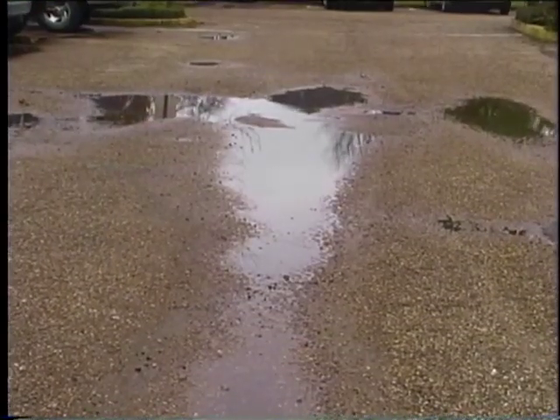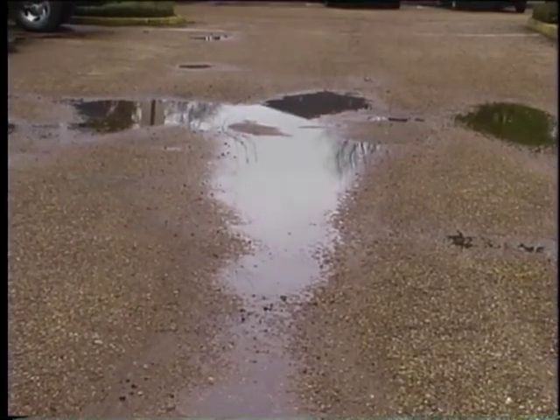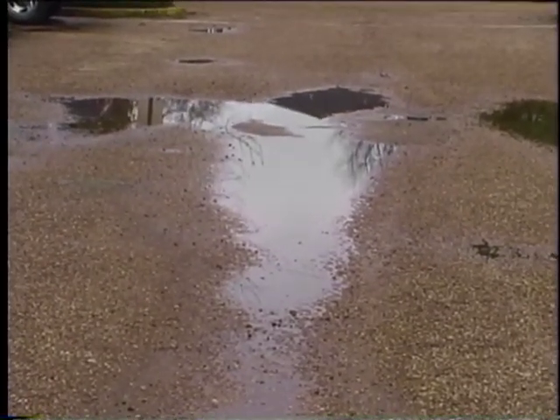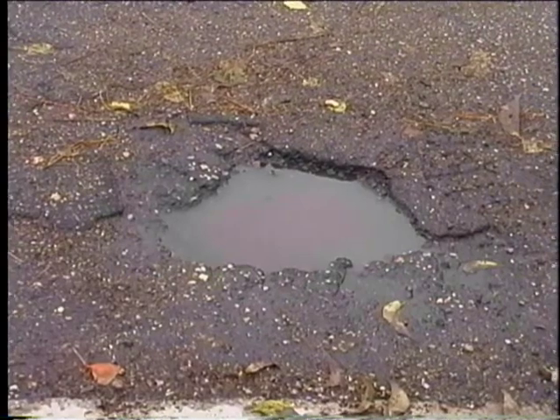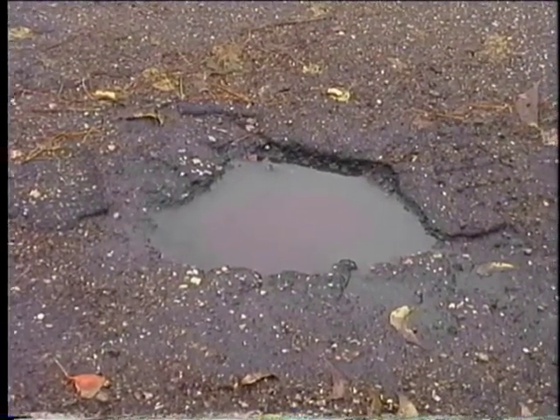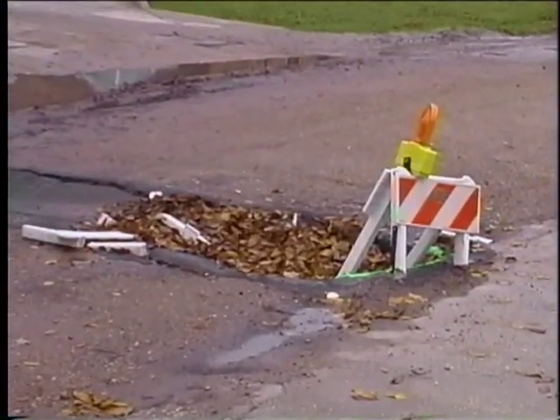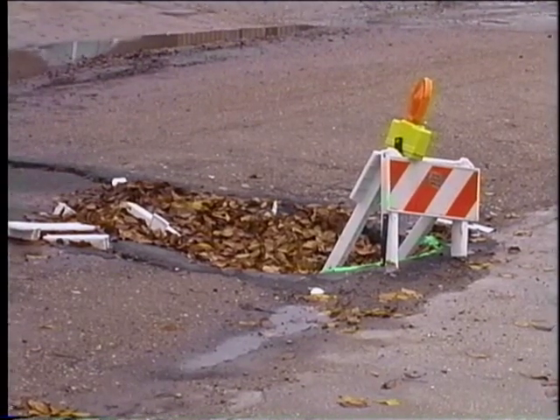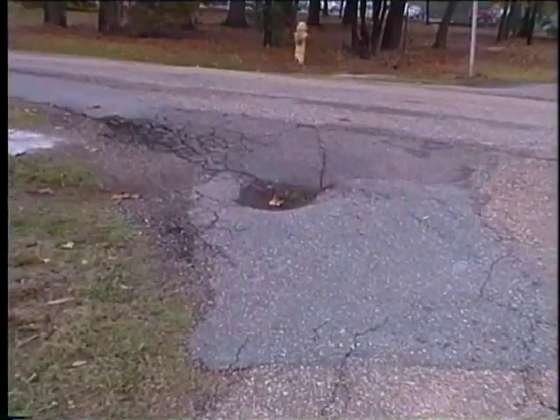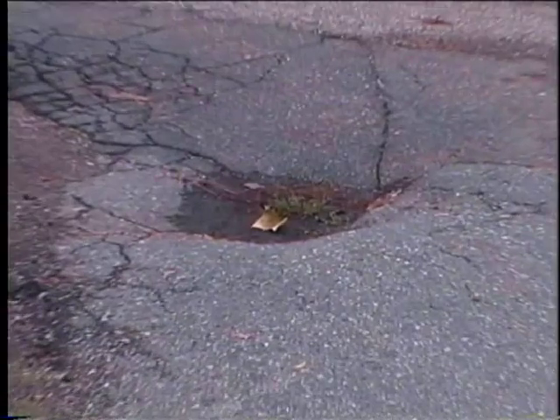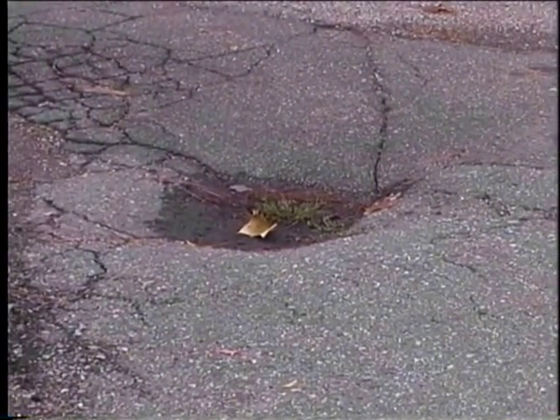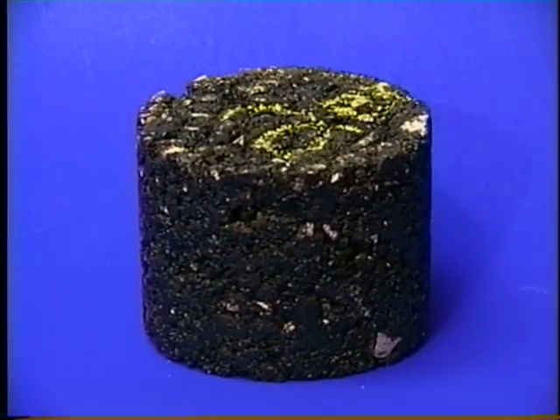Under ideal conditions, the material would be impervious to surface moisture. If water enters the HMA mixtures, it may cause stripping, which will damage the aggregate asphalt bond. A high number of air voids will lead to a permeable mixture that will allow water to enter the HMA. If these air voids are interconnected, water will flow through the HMA.